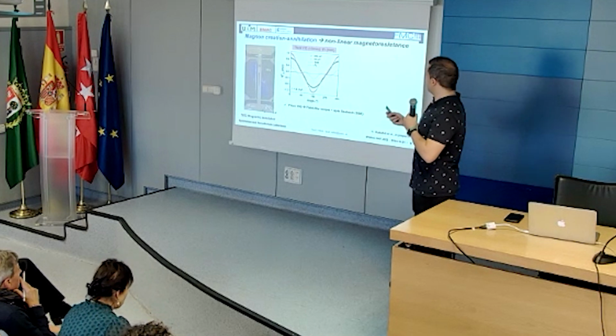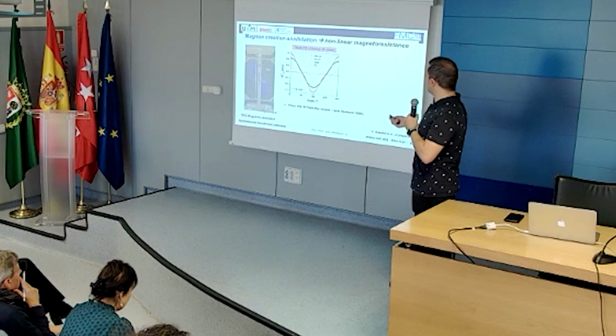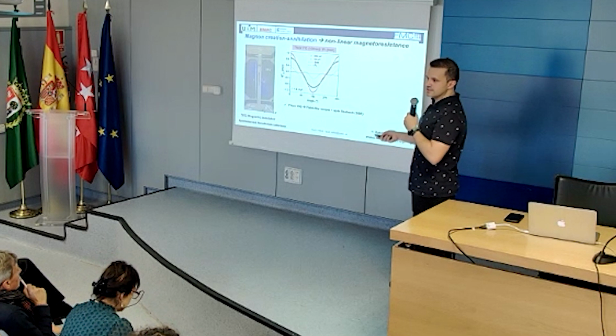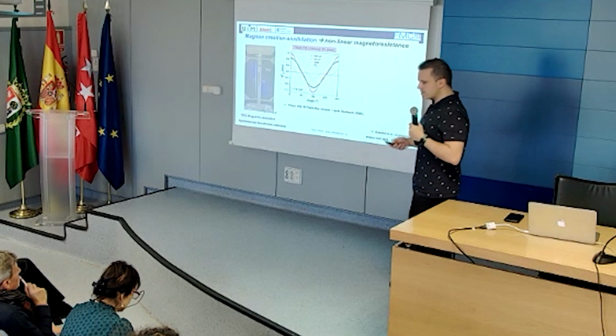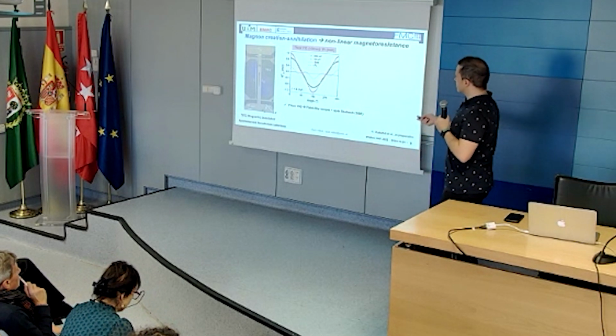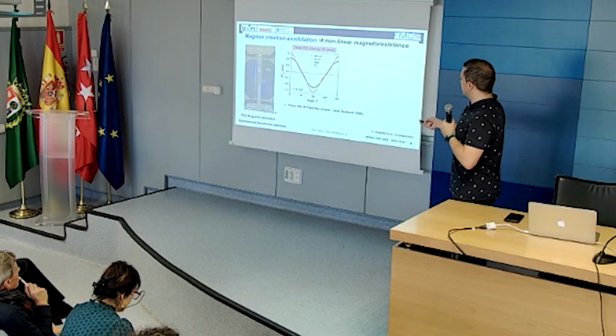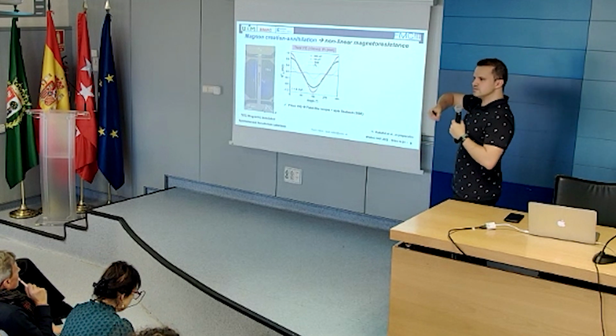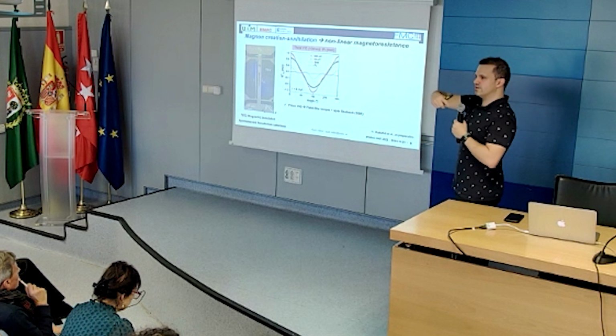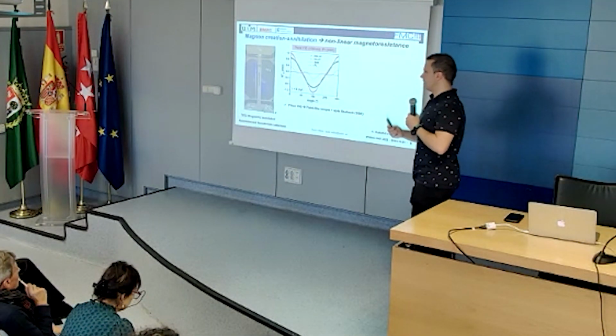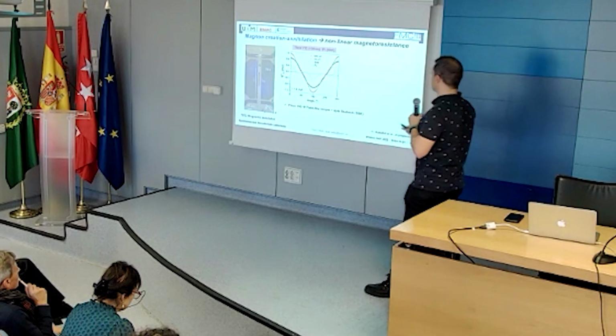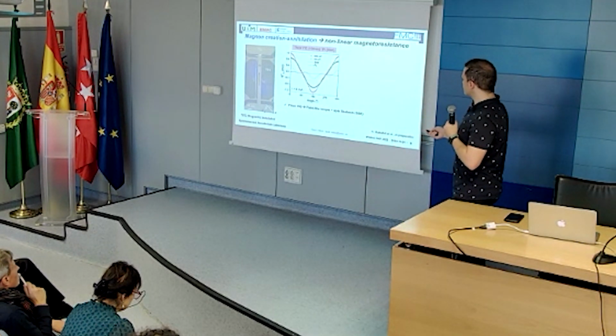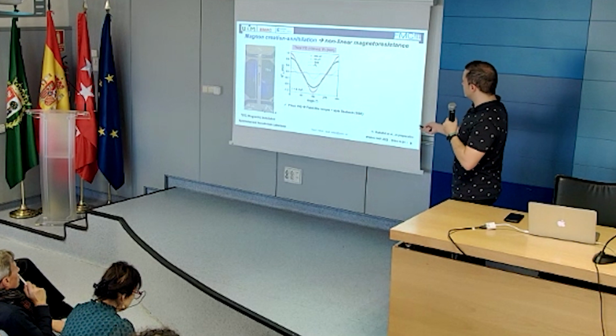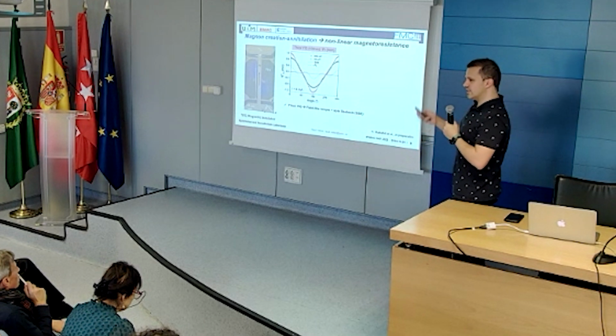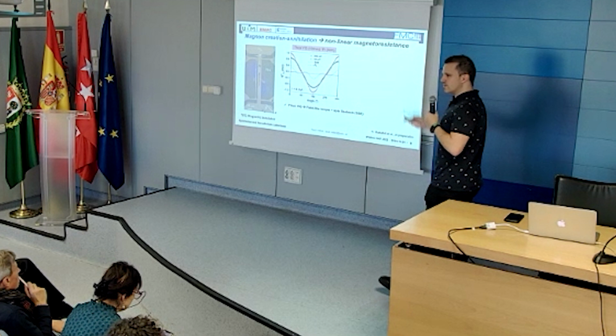So then you see this damping torque. For the large field, 400 millitesla, you only see the thermoelectric effect. That's the spin Seebeck effect. I'm not going to explain how this works now, I'll show you a little bit later. But in the end, it's like a thermal gradient out of plane, and depending on the direction of the spin, you are pumping spins into the platinum, and that's what leads to this non-linear magnetic effect. And then on top you have this field-like torque that you measure when you have small fields, and that's very strongly dependent on the field, particularly 1/B.